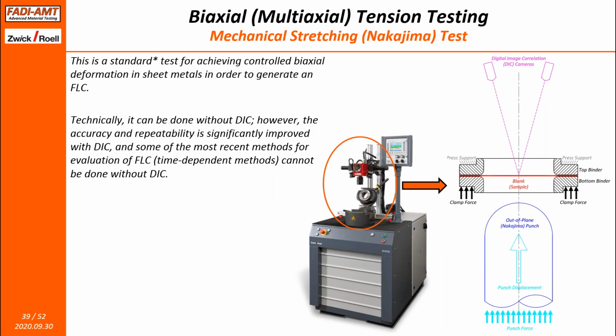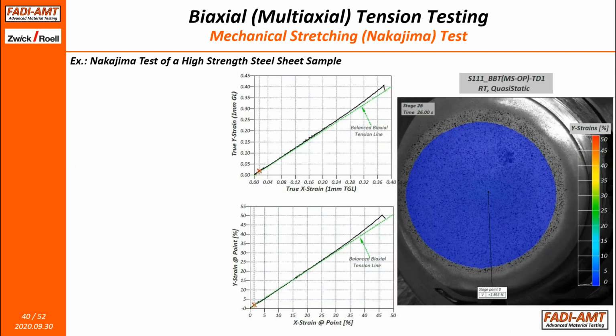But how can this test be done with and without the DIC? In essence, you can do these tests without the DIC. In fact, they can be done without any extensometry per the standard. The ISO standard dictates that you can do it in a post-deformation mode. However, it's not actually very accurate. And so the use of extensometry, non-contact extensometers and/or DIC will help improve the accuracy and the repeatability of these tests. In very particular cases, only DIC can be used in order to provide a certain type of outcome. And I will explain a couple of them, including basically the FLC generation with the new methods.